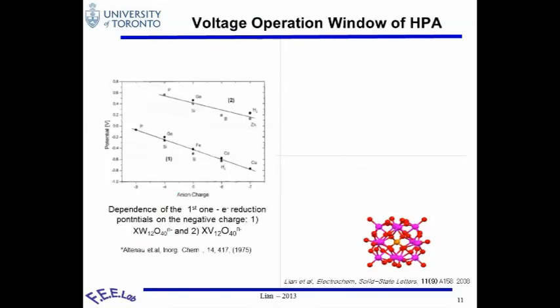The answer to this is coming from this graph, published earlier in 1975. What's interesting about this graph is it shows that in the heteropoly acid form, you have a heteroatom in the middle, surrounded by these pink ones, which are the transition metal ions and oxygen, forming a cluster with a special stable structure. This graph shows that by changing the heteroatom in the middle, you reduce or change the first electron reduction potential. So from phosphorus to silicon to boron, the first electrochemical reaction window starts going more negative. What does that mean?